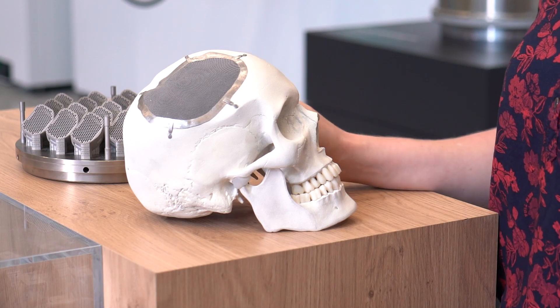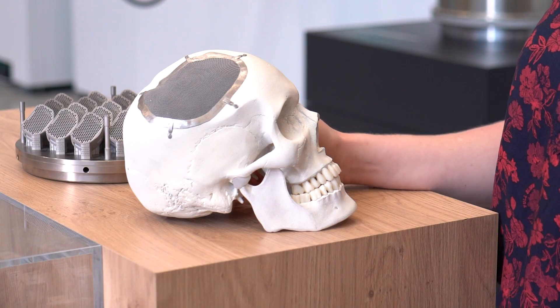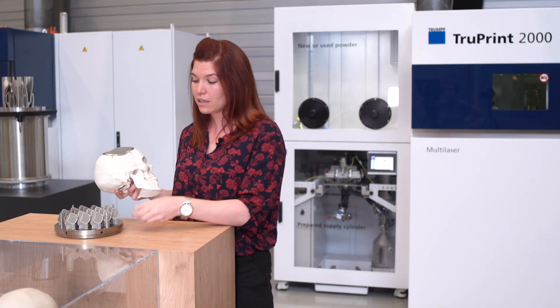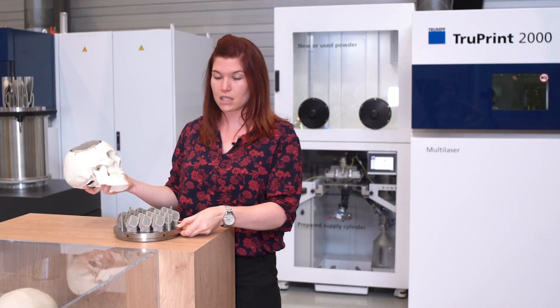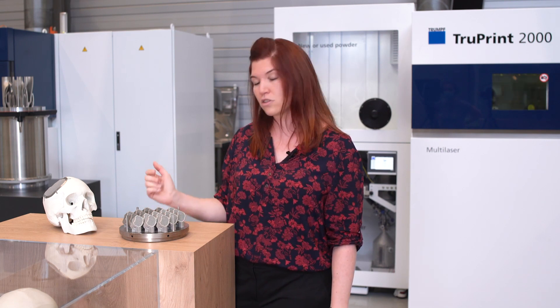In general, patient-specific implants cover a smaller percentage of 3D printed devices. What is more common within the industry is the manufacture of standard devices, like acetabular cups or spinal cages. These applications benefit from the freedom of design as well — it is, for example, possible to create specific lattice structures or porous structures on the implant that can improve osseointegration and implant anchorage.